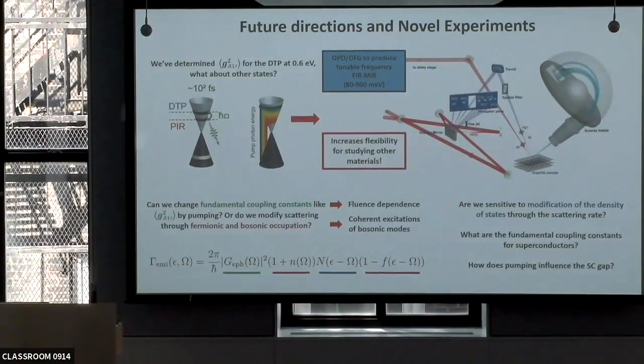It's actually interesting to look at the scattering rate for the process we were looking at in a more realistic way, where not only do we look at the coupling, but also at the electronic density of states, the occupation for the phonon, so the phonon population, and for the electrons. And so basically, by playing with different conditions, we could play with all these different terms and see what the effect is on the quantities that we extract.